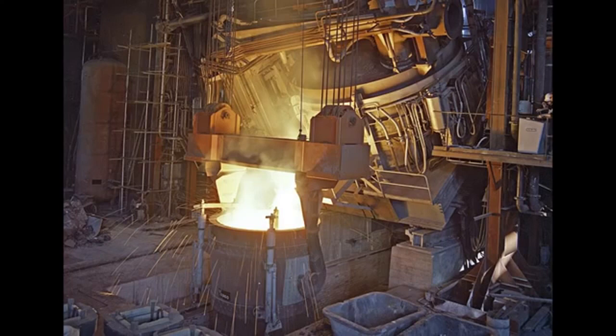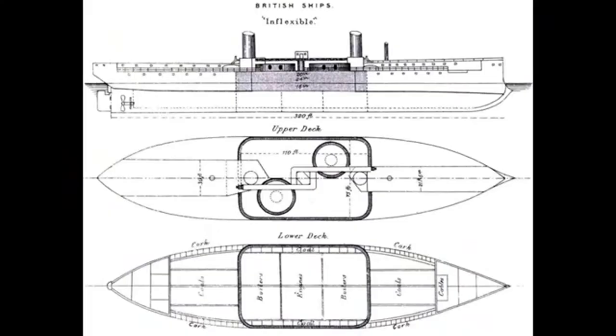Fortunately, the system of testing before construction was now fully in place, and so when the test showed that the steel was far too brittle for practical use in ship's armour, it was put aside as an armour material, at least for now, without any classes of steel-armoured warships being prematurely laid down. However, as time marched on, there were physical limits to what you could do to strengthen iron, whilst gun and shell technology just kept on going.